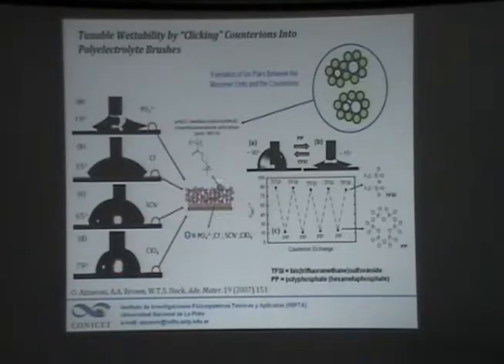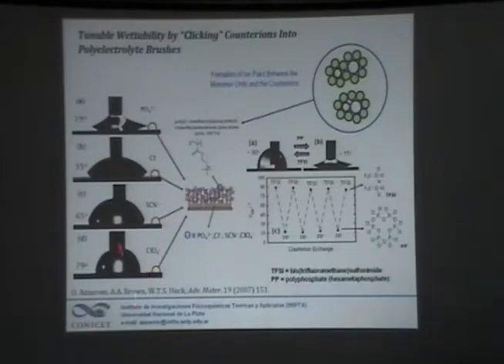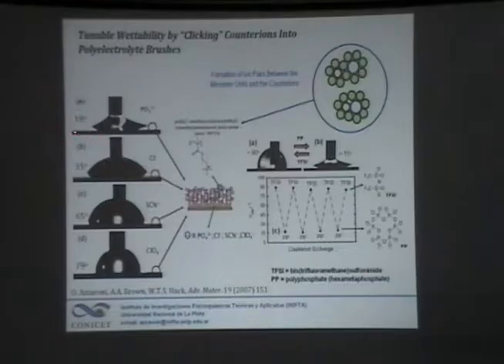By growing exactly the same brush with cationic groups, you can exchange the counter-ion using very simple aqueous chemistry — just put a substrate in a beaker with an aqueous solution of the ions — and you can tailor the contact angle of that surface. The same surface can come around in a range which is between 19 and 79 degrees.